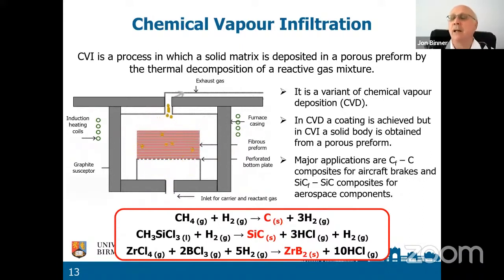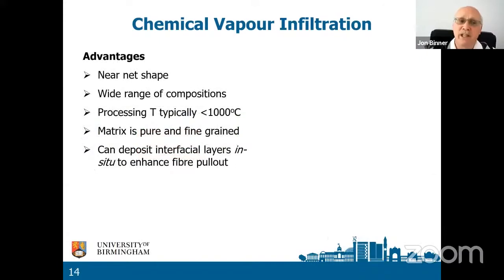And CVI is a commercial process. It is how carbon-carbon brakes are made for commercial aircraft. This is the process by which aircraft brakes are made. And also aerospace components are made out of CMC composites using the same basic process. The advantage is a near net shape process. There's a wide range of compositions. The best one is that the processing temperature is typically less than 1,000 degrees centigrade, and that means you don't risk damaging the fibers. The matrix is pure and fine grained, and in situ, in the process itself, you can put different gases through. So you can start by depositing an interfacial layer, and then you can change the gas and deposit a different matrix. So these are all very good advantages.